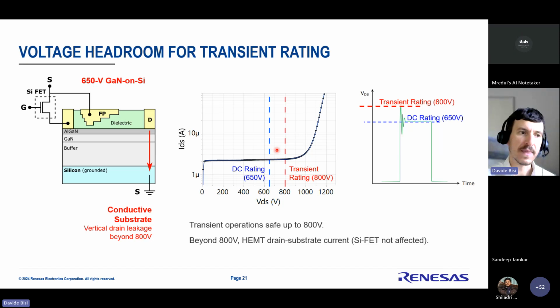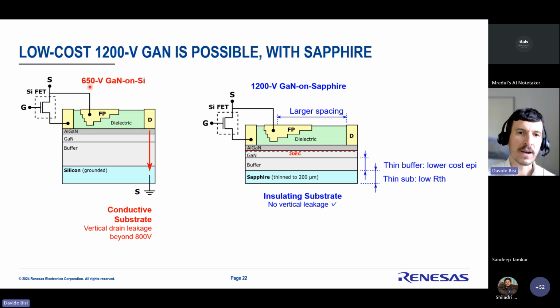But of course, the industry is requiring not only 650 volt devices, but also 1200 volt devices. And that's where Transphorm had the insight, a few years ago, to design a 1200 volt lateral GaN HEMT. And to do that, the idea was to replace the conductive substrate, like silicon, with an insulating substrate, like sapphire. So with sapphire, which is insulating, we are basically eliminating the leakage path between the drain and the substrate, therefore further increasing the voltage rating of the device. And a few things here. The sapphire is known to have a higher thermal resistivity.